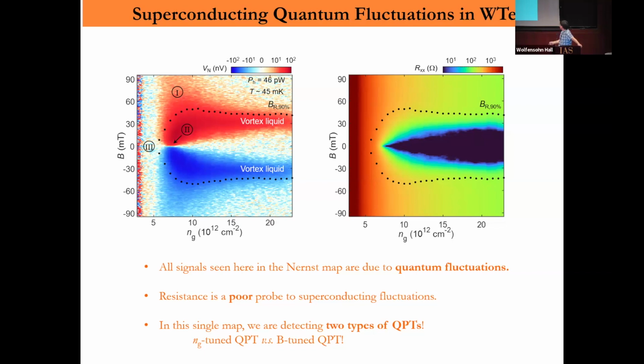So one important note is that this fluctuation you see here all comes from quantum fluctuations, because if I warm up, all the signal disappears. This is maximized, the signal is maximized at the lowest possible temperature. And temperature here I keep at 50 millikelvin, the lowest possible. So everything has quantum fluctuations.